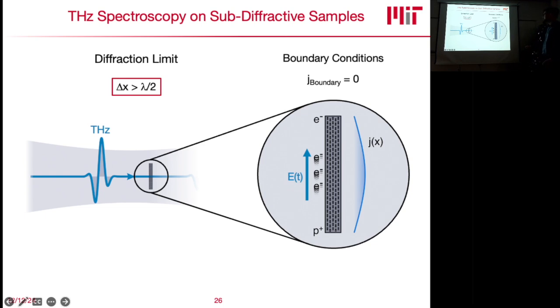If you take, for example, this small slab of material, let's call it metal, and you start displacing your electrons, what will happen is you get a shape of the current that is terahertz induced in this material like this, where you have nodes on the sides and a maximum in the middle. And so this charge accumulation will actually lead to an active restoring force on these otherwise freely flowing metallic charge carriers, which will move your response from zero frequency up to a high frequency. So you go from a so-called Drude-like metal to something that resembles more bound charges or plasmons.